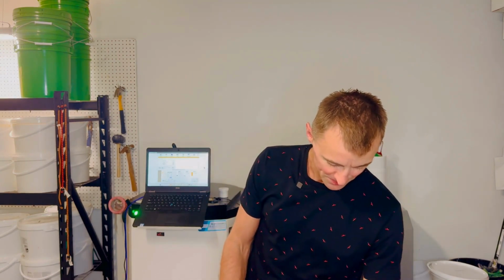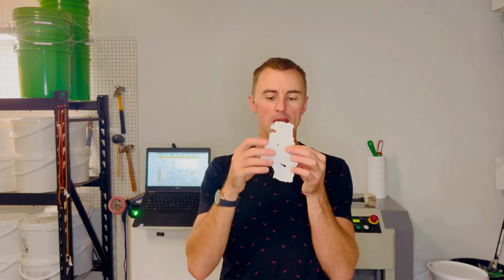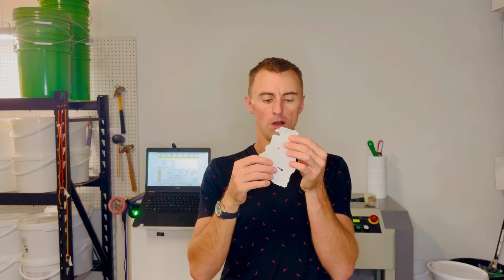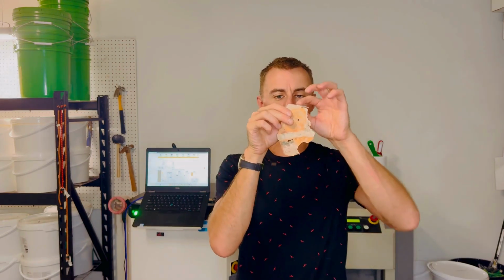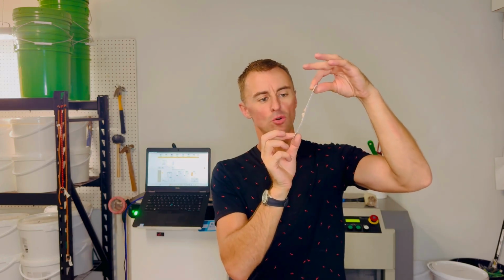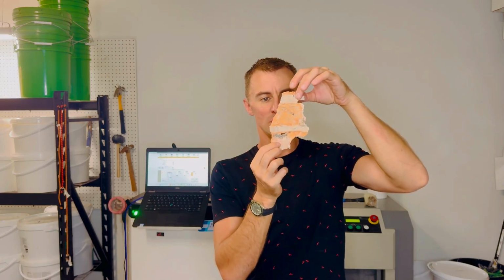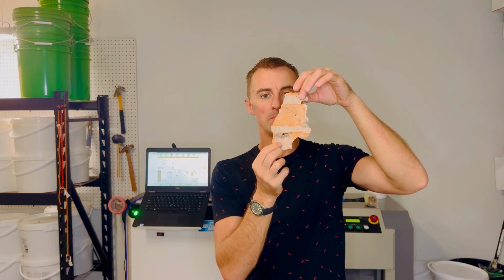So today I want to go over how our products differ between latex, acrylic, or elastomeric paints. So let's get started. In this article we will notice this is a latex paint that was used to pull off of a building in Fort Myers, Florida, which we know has a high content of moisture. If we look at the back of this, you will see how the mortar and the actual orange brick, after a while and multiple coatings, is just getting pulled off with failing paint.